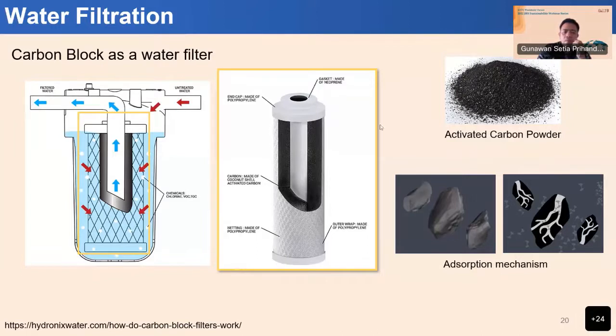Therefore, some companies are trying to develop carbon blocks. With a carbon block, there is less chance of the pollen passing through between the powder, because the powder is completely attached together. So a carbon block is better for the water filtration process. The only problem with the carbon block is that it is difficult to make. They use a high temperature furnace and a high pressure system to make sure the block is completely pressed and compact. So it cannot be made by a home industry or a small lab.